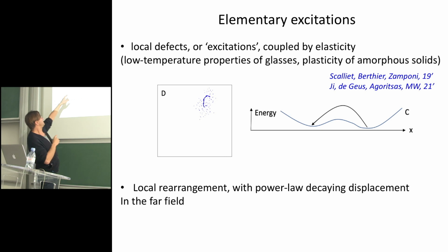And so what you find if you do that are local rearrangements of a few particles, okay? In the energy landscape picture, along one direction, you jumped over one barrier. So we pay attention that our algorithm just jumped over one barrier, actually. So it is a local rearrangement of a few particles, but it's also interesting to notice that it is an elastic medium. If you have a local rearrangement, it will have a far field response. The stress will decay as a dipole, like 1 over r to the dimension of space, and things like that.